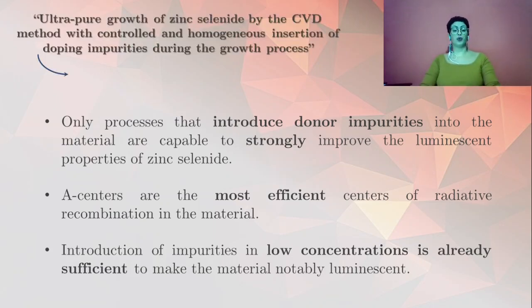Finally, this work indicates the ultra-pure growth of zinc selenide by the CVD method, with controlled and homogeneous insertion of doping impurities, aluminum for example, during the growth process, as a successful methodology to produce zinc selenide crystals with good luminescence desired for its application as a scintillating bolometer.